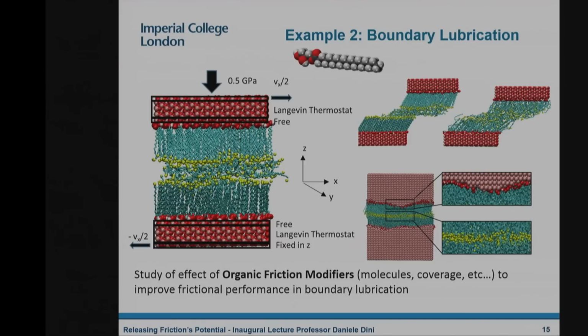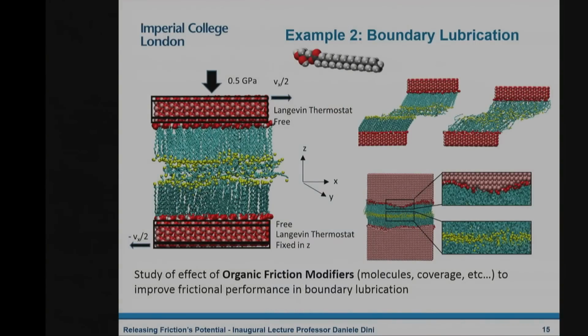And here we've explored the effect of specific additives again, organic friction modifiers, when they are adsorbed on the surface. Here you're looking at very nice iron oxide surfaces. They don't really look like that, but in a computer model they do. And here you've got adsorbed some fancy molecules that are put there to reduce friction. And the idea of this study was to try and understand what's the mechanism by which you end up reducing this friction. And to do that, we did a lot of different simulations, starting from looking at how, if you take two surfaces and you squash them together, whether or not they've got some roughness on it, and you try to shear them, once you apply very large pressure, you get a certain frictional response.